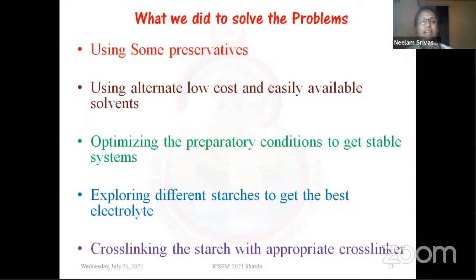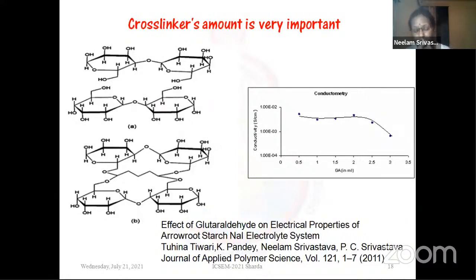So we have tried different methods using some preservatives, using alternative low cost solvents available, optimizing the preparatory conditions, exploring different starch, and cross linking the starch with the appropriate cross linkers. In all these methods, we found that cross linking the starch with the appropriate cross linker is a very simple and important method. And for this, if you see this, this is the starch matrix, and these hydroxyl moieties are used for the interaction with the salt. But when you put GA in the system, the glutaraldehyde we have used as a cross linker, this GA interacts with these moieties. So it has been observed that the amount of the GA is going to affect the conductivity of the system. So it has limited us to use a compromised value of the GA to achieve a highly conducting system.